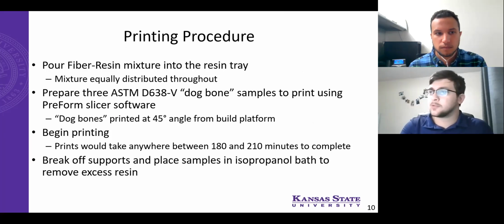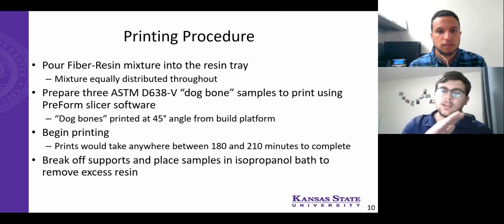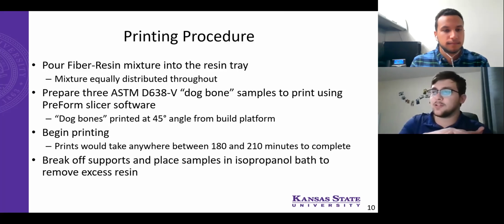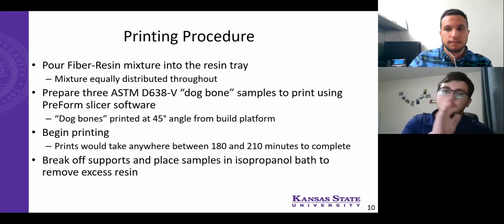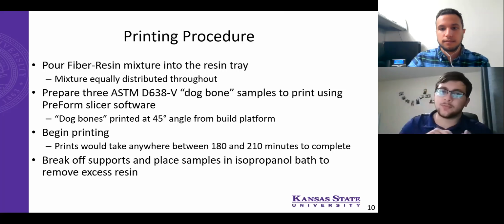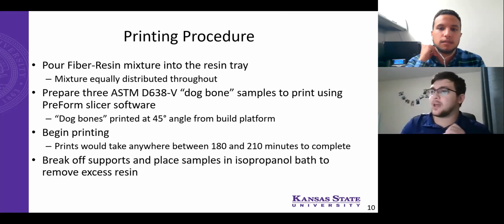So then we pour the fiber resin mixture into the resin tray. We use the PreForm slicer software to prepare 3 ASTM D638-V dog bone samples. And we printed those at 45-degree angles. This was to make sure that the adhesion wasn't too great if it was just plain flat against the build plate. And also at 90 degrees, it's possible the weight of the dog bone would pull it off of its own build platform.